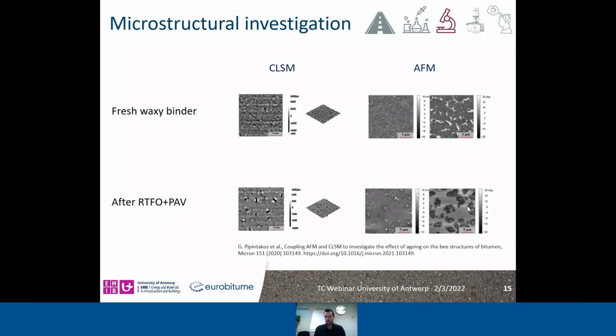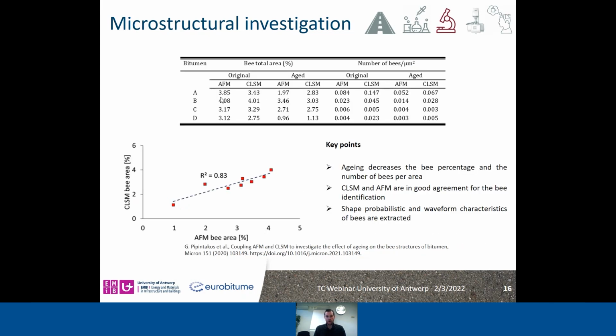And with AFM, with phase contrast, we can also observe a second phase of these bee structures, which is called the periphase, which is not really obvious with the confocal laser scanning microscopy. After that, let's say, human-based observations, more sophisticated image editing software packages were used that accompany these two microscopies. And we were able to isolate the bees based on height thresholds that were imposed for the peaks and valleys. And we extracted for the waxy binders before and after aging different metrics of identification of the bees, like the bee percentage and the number of bees, which are normalized per square micrometer.